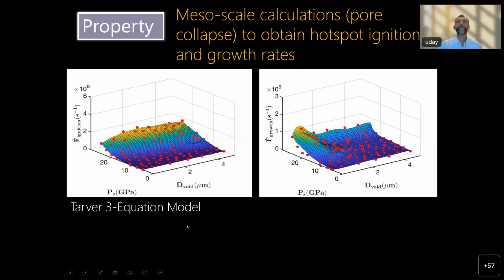In the property part, what we do is we construct these hypersurfaces for the ignition and growth rates in the space spanned by the shock pressure and the void diameter. So we're doing single void simulations. We are varying the diameters of the void, we're varying the shock pressures, and we're collecting data, and we use what's called dynamic kriging, which is a kind of GRP approach, Gaussian random process approach, to construct these hypersurfaces. So these hypersurfaces tell us about the meso-scale sensitivity of the material. That is, if you subject one pore to a given pressure and the pore is of a certain size, what is the ignition and growth rate of hotspots from that one pore?